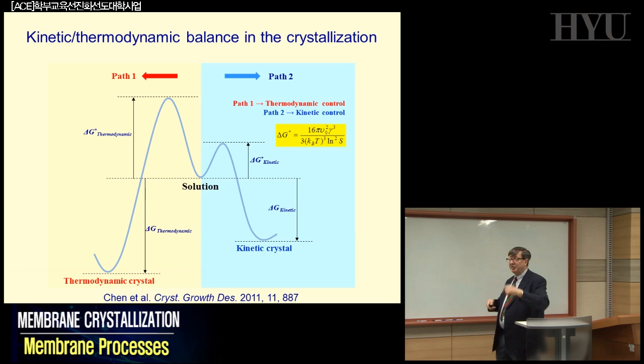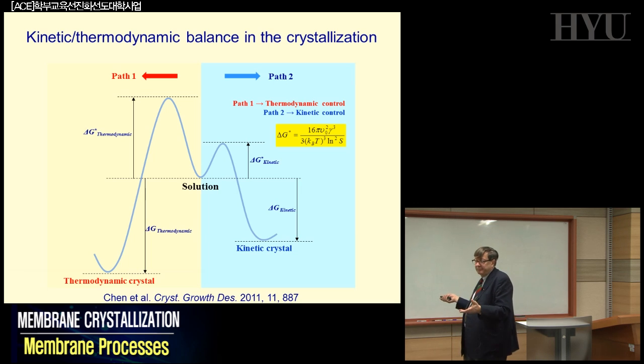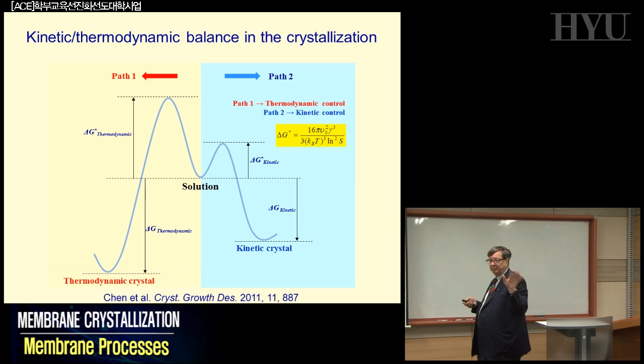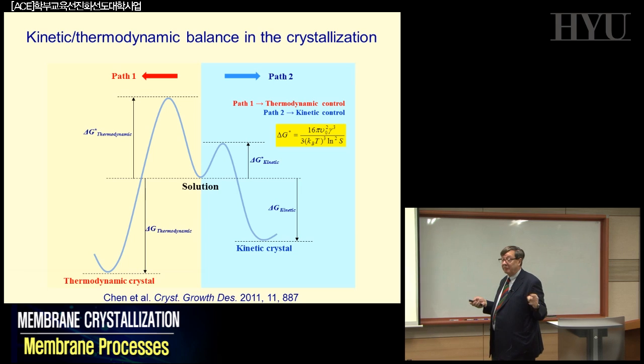And depending on the velocity at which they form and disappear, eventually, in some cases, you can have some effect, but normally negligible. If you are using membranes in your crystallization, what is happening? You are changing not only the kinetics of the thermodynamic phase, which at the end will be the same, but you can have a significant control on the metastable forms that you are creating in the metastable phase. Now, if you reduce the activation energy of some of the metastable phases, you would crystallize them very quickly. So they will never arrive at the thermodynamically stable phase at the end.